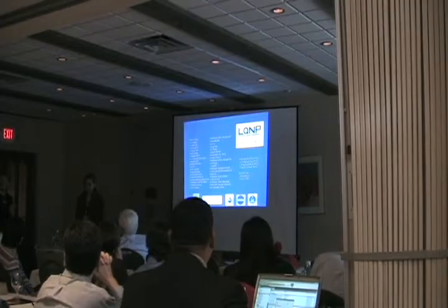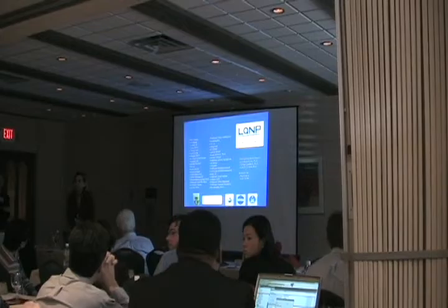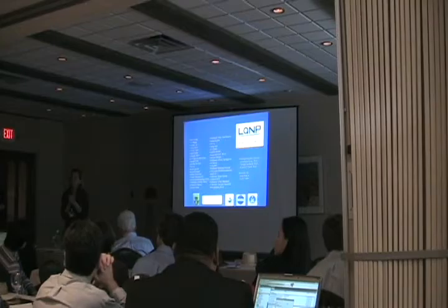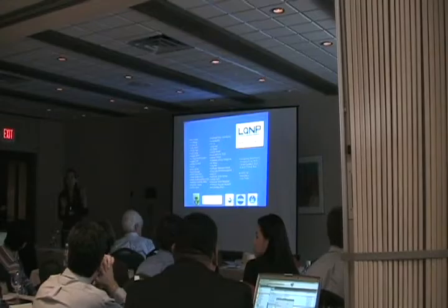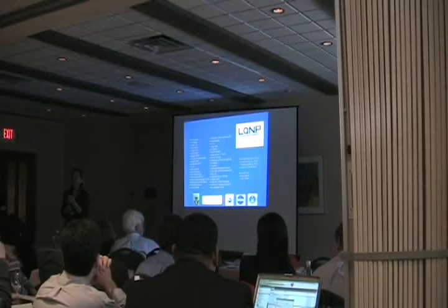What causes the nanoshells to localize to the tumors? It's a property of the tumor. Are they derivatized with some molecule? That can be done, and that has been done, but it turns out that particles as small as about 100 nanometers will accumulate naturally inside the tumor. Liposomes do exactly the same thing. People have known about that for decades. They've used that for drug delivery.